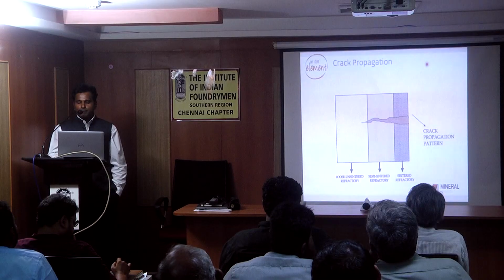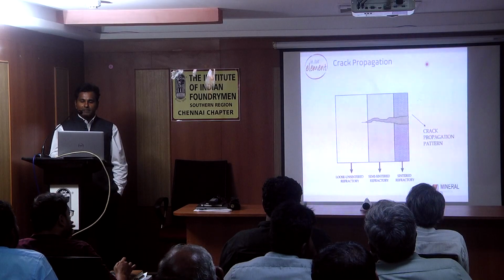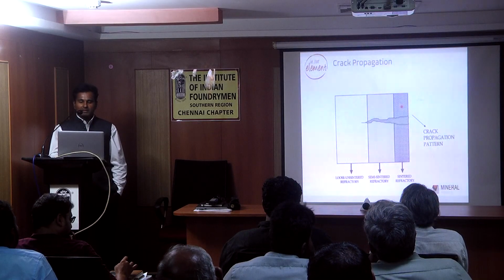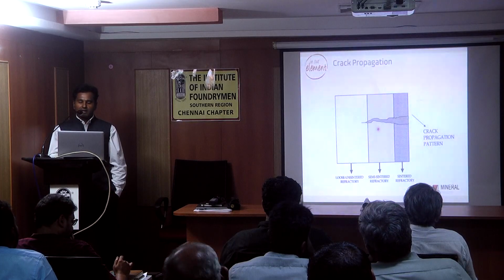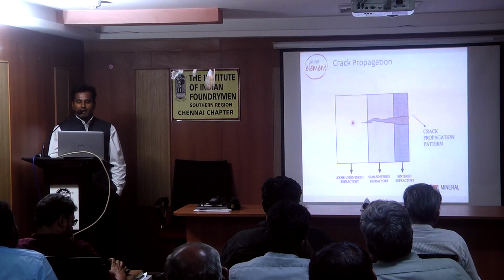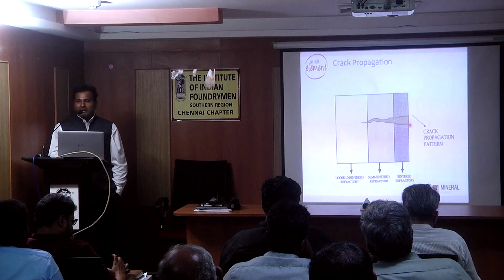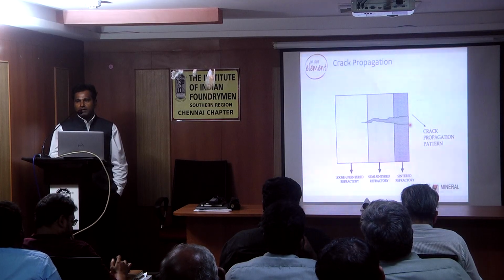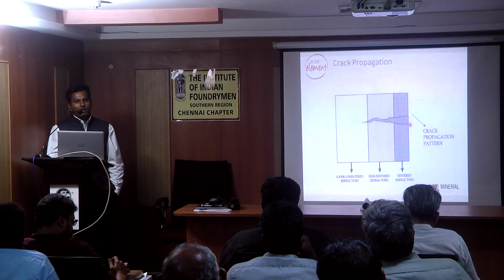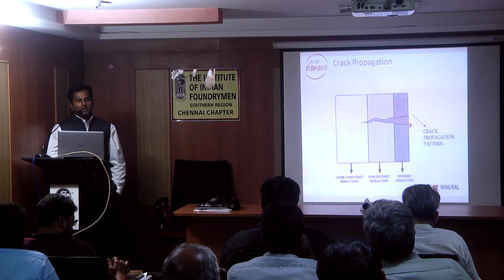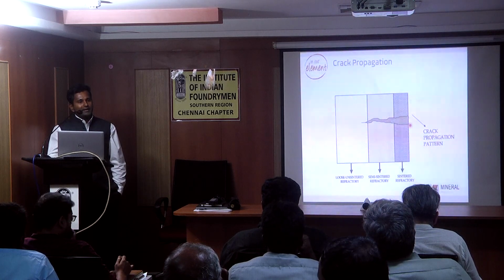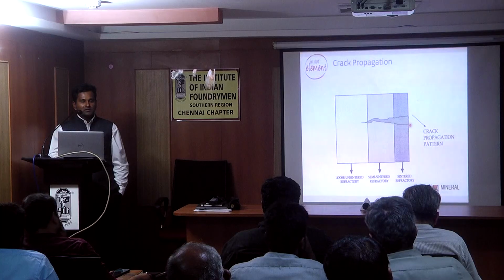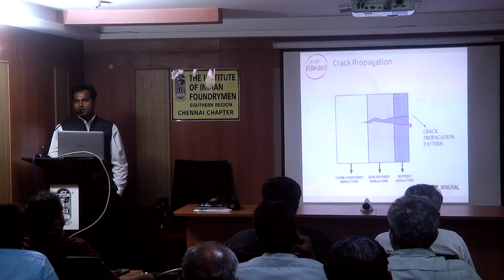This is how the crack propagation starts. It propagates from the hot face, slowly enters the semi-sintered refractory, and goes to the loose backup. Metal expands 3 times more than the refractory. So whenever there is a fin already present in your lining system, it will slowly travel towards your coil very fast. This will lessen your overall lining life.